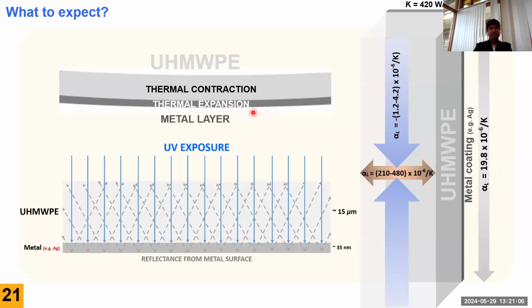So there will be a gradient of thermal expansion and contraction, which tends to create a bending or a curve in the film. And what we are anticipating is that if the light passes through the film, because of these metal coatings, such as silver, these light rays or photons will be turned back into the film, thus increasing the actuation stress.